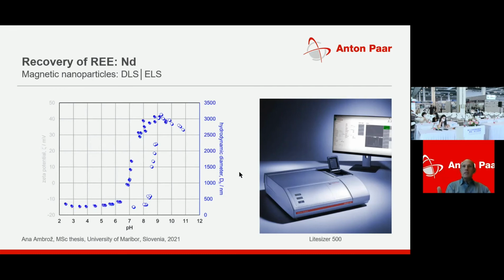By decreasing the pH, we observe some reversibility of the particle size, but also a kind of hysteresis, which delays the approach of a particle size of 250 nanometers to a lower pH of 6.